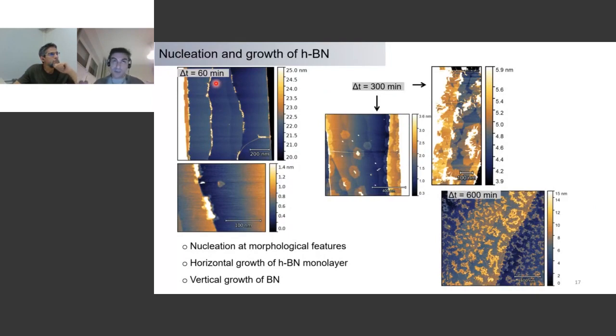Basically, we are keeping the flux of boron and nitrogen constant during growth. We are also keeping the temperature of the substrate, of the graphene surface, the same, in this case 850 degrees Celsius. And then we start growing first for 60 minutes, and we see almost nothing at the surface. It's still like pure graphene. We just see some islands that seem to be forming close to surface irregularities, like step edges or wrinkles that we have at the surface.